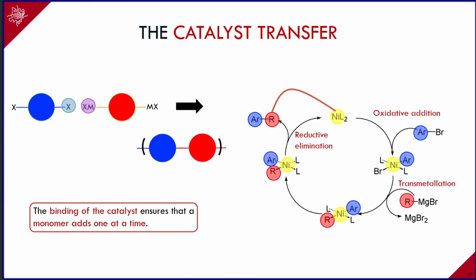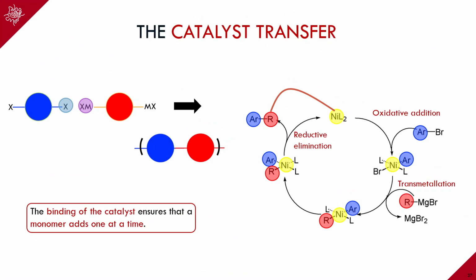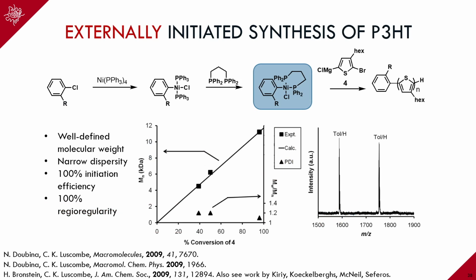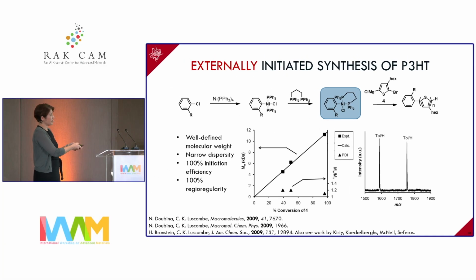The chemistry that we developed in my group is the following, of attaching the nickel onto this growing polymer chain, and by doing so, we get this one catalyst addition at a time. I won't go into detail on this slide, but here is the catalyst that we made, monomer addition, and the polymer grows really well. And this is a graph that only a polymer chemist would be happy about. But what this really shows is that you have perfect control over the molecular weight. The squares are the experimental data points. The solid line is the theoretical expected molecular weight. So you can see we're controlling the molecular weight.